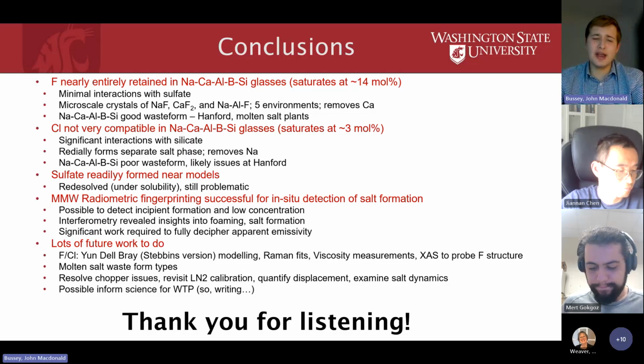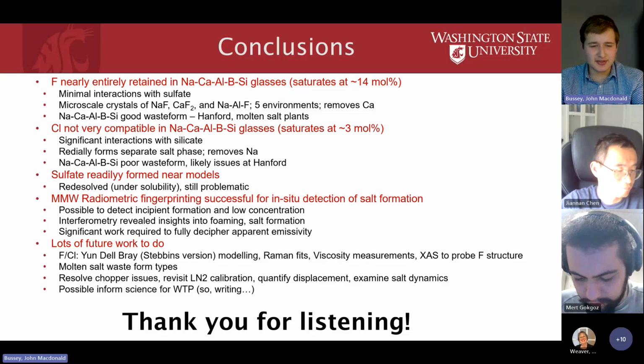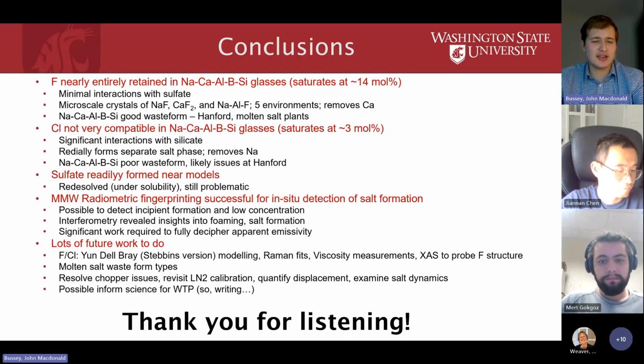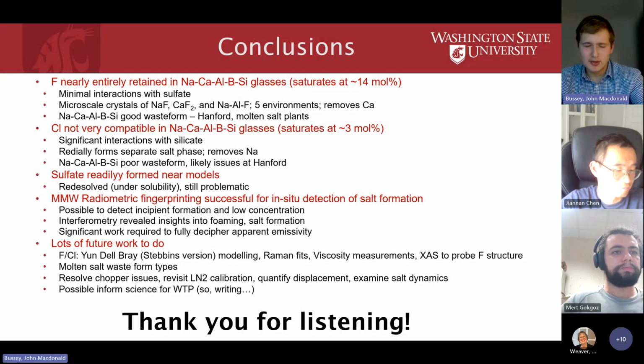Back over to the millimeter wave radiometry, this fingerprinting we did was successful. So we showed that it could work in an in situ situation, which is great. We also saw that the interferometry can give us insights into foaming and salt formation, which is also helpful. And we were able to do this at fairly low concentrations of salt with only partial coverage on the surface. So probably can detect some incipient right at the very start of formation.